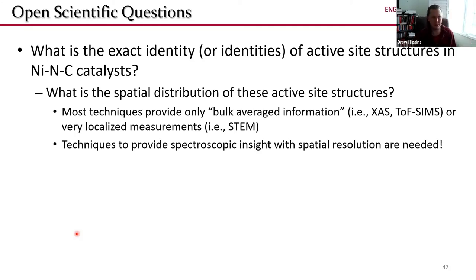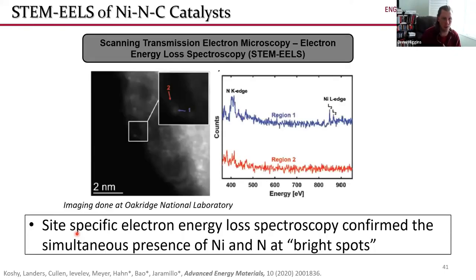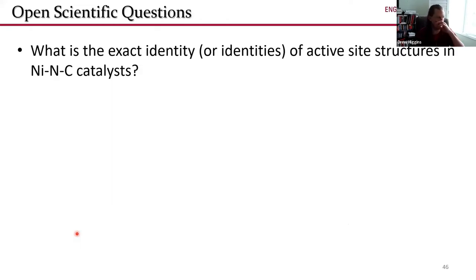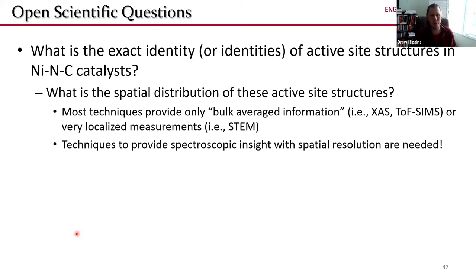Or the other measurements that can be done, for example, transmission electron microscopy, provide very localized measurements. So you're looking at one single catalyst particle among millions. And even within that, you're looking at an area of about 4 nanometers squared of your catalyst material. So you don't get an idea of what the meso or the macro structure is of these catalysts, or what type of active site structures they have and where those active site structures are located. So what we really need is techniques that can provide spectroscopic insight with spatial resolution.